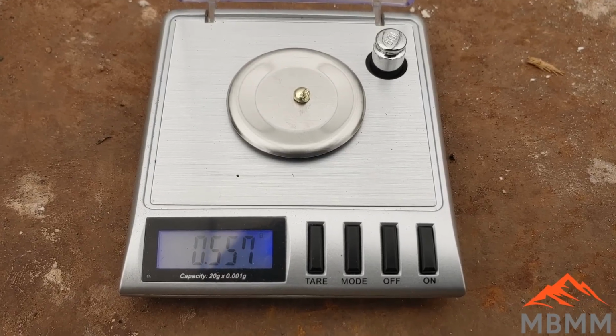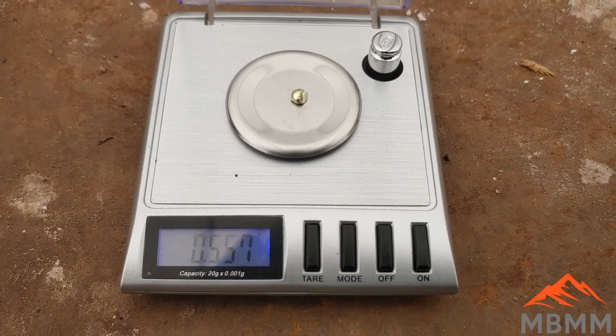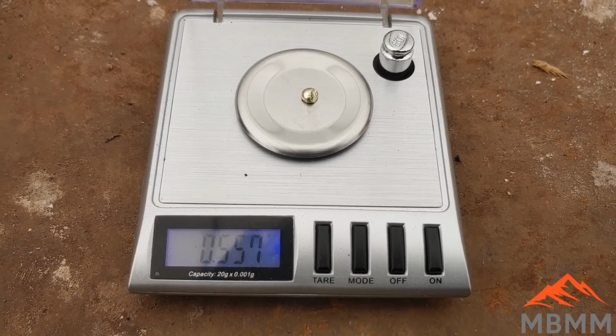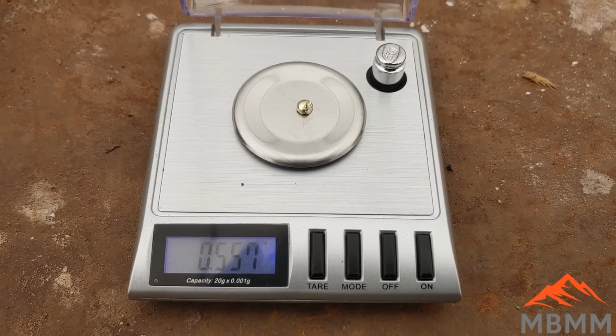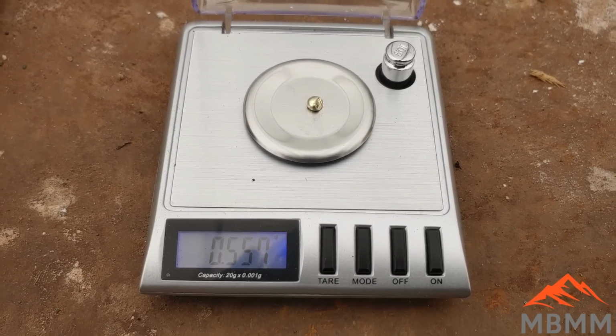And here's our little bead from that 100-gram sample we did after we recovered a gram of gold. So there's a significant amount of gold left in our matte. So at this point during the video, I'm pretty disappointed. I realize now that with the copper matte that we have, I'm not going to be able to just convert it all to iron sulfide and recover the precious metals. There's still precious metals locked up in those sulfides, and there's not going to be a really easy way to deal with it. So I'm going to stop it here for part one.